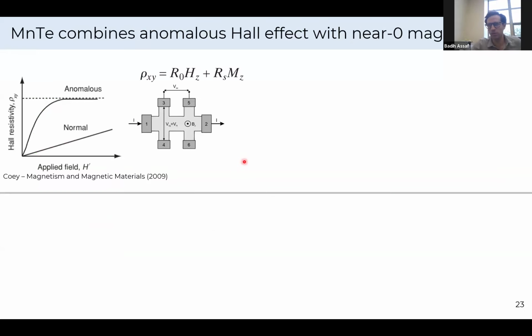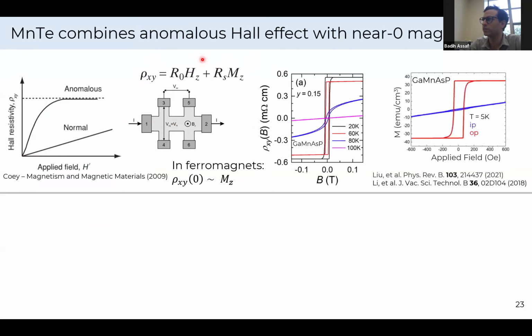Now we go on and we measure the anomalous Hall effect. We can pattern Hall bars, stick contacts on them, and then you apply a current along this direction, field perpendicular out of the page, and then you measure the transverse Hall resistance. Naively speaking, what you expect from the Hall resistivity is for it to scale proportionally with magnetization. At least that's the picture for conventional collinear ferromagnets.